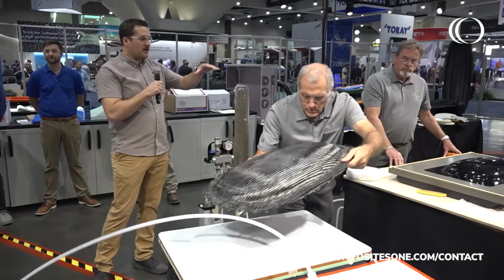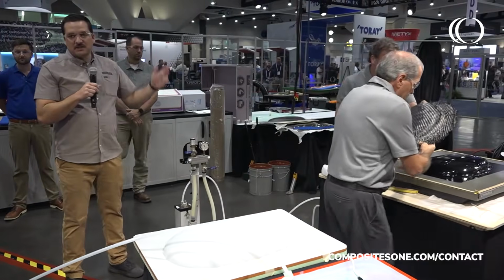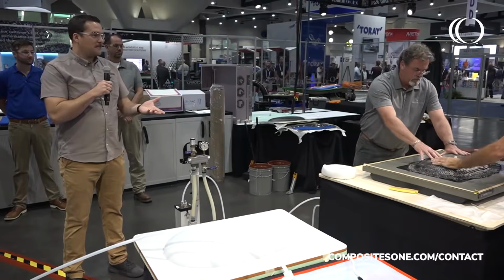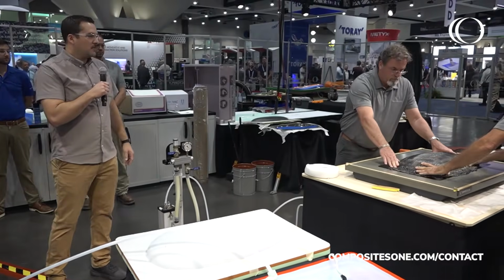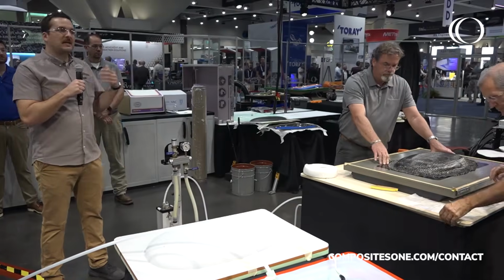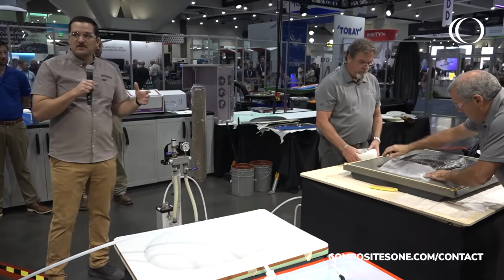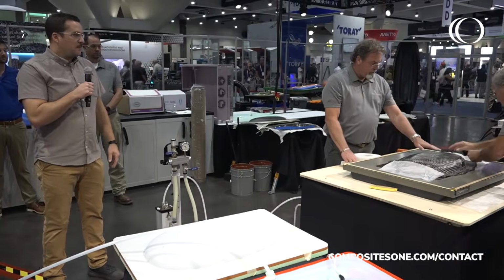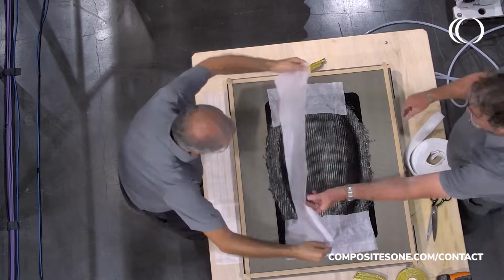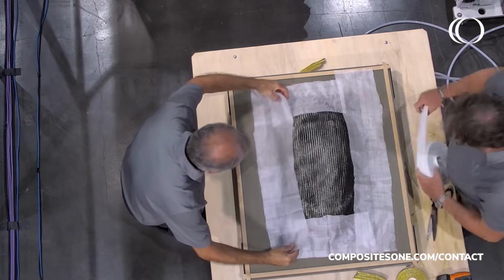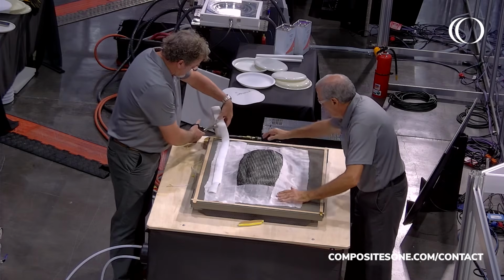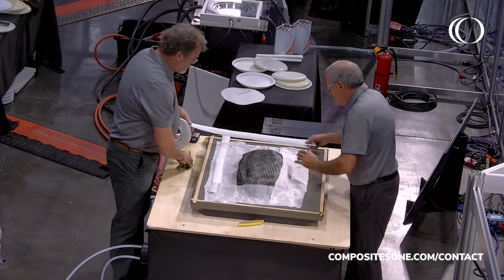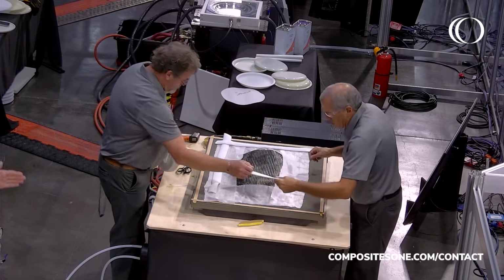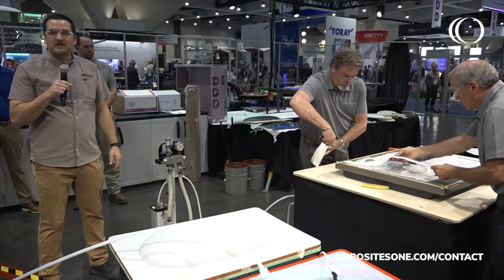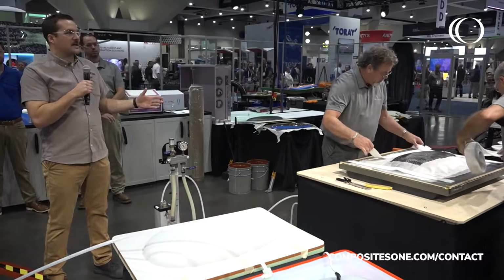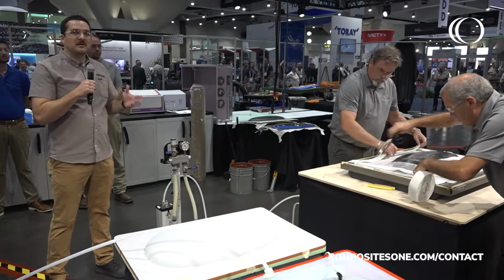As James mentioned, it is a two-part construction. It has a sandwich structure, as you can see in the slide. We create a separate base plate out of 6061 aluminum. We obviously have a scale factor, and we always need to take into account the temperature delta when we're producing these tools to get our dimensional accuracy. Once we go through that design process, we take into account the stresses involved with the pressurized water system, and we design the circuitry. We basically have a water feed in, a water feed out. It's a very simple system. It's very friendly to use, and it's also very scalable. With this system, you're able to scale up multiple tools, but furthermore, you're able to reduce cycle time. Speaking to Barry, he was able to take his cycle time down from 2.5 hours to under 40 minutes. So it's a significant cycle time improvement.